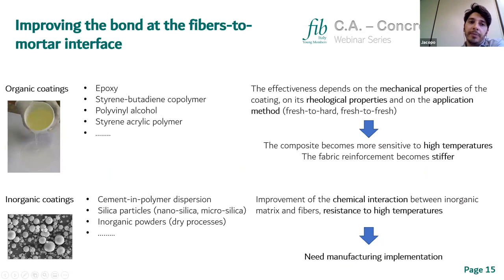In the last years, a lot of attention has been given to improving the bond at the fibers to mortar interface. We can do that, for example, by modifying the mortar composition, adding organic polymers. Or we can do that by improving the surface of the fabrics with organic coatings, which can be epoxy resin, but also styrene butadiene copolymer, polyvinyl alcohol, and so on. This is the easiest way of improving the surface of the fabric.